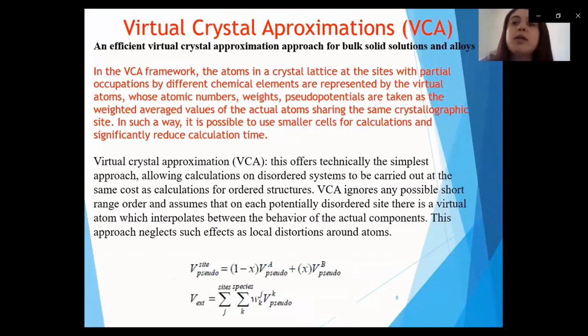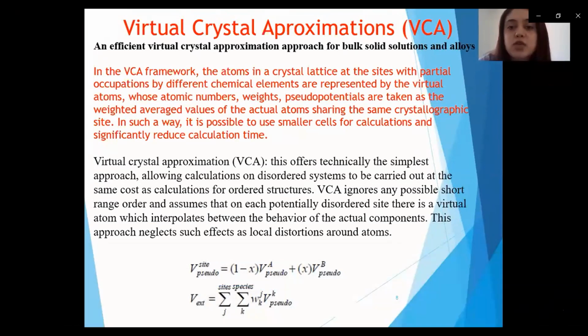Virtual crystal approximation. In the VCA framework, the atoms in a crystal lattice at the sites with partial occupations by different chemical elements are represented by virtual atoms whose atomic numbers, weights, and pseudopotentials are taken as the weighted averaged values of the actual atoms sharing the same crystallographic site. In such a way, it is possible to use smaller cells for calculations and significantly reduce calculation time.